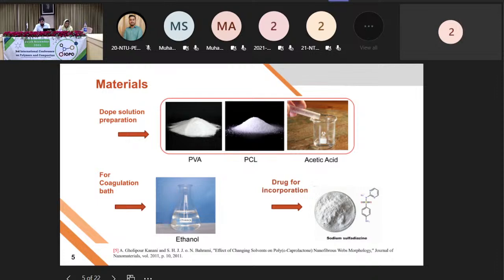So in the first phase of this process, we have developed the fibers, analyzed their properties, and observed the best possible concentrations or blend ratios at which the best possible properties are achieved. Using that optimized material, we incorporated a drug at the optimized blend ratio. Regarding the drug, we included sodium sulfadiazine as a model drug in the dope solution. We then extruded that drug-loaded material into the coagulation bath and tested it for drug delivery applications.